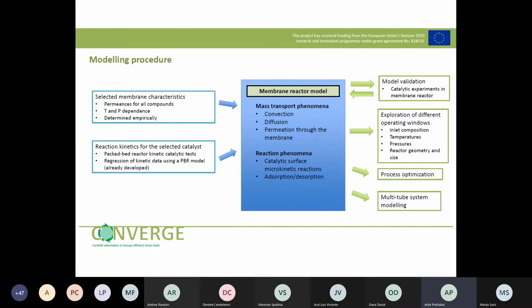Our part is also modeling of the system. To describe the reaction system, we first focus on membrane permeances, where we develop empirical relations for pressure and temperature dependencies of permeances. The catalyst activity is separately measured in a packed bed reactor, and a microkinetic model is used. The model of the membrane reactor itself is presented in more detail in the next slide. The model will be validated using experimental results and then used to find operation windows which are preferred for the membrane system. In this way, modeling can provide feedback information on further membrane permeance or reactor geometry improvement. The optimized conditions can be used during the operation of the TNO multi-tube system, which will also be modeled.